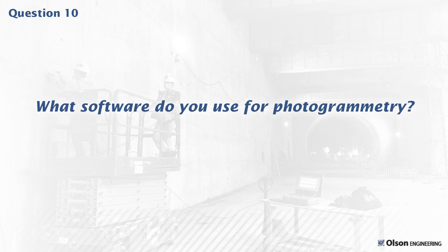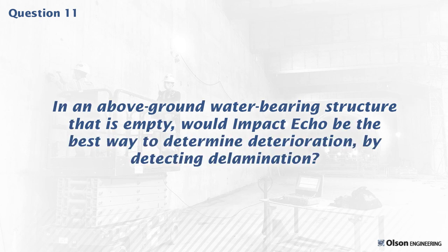Q: In an above-ground water-bearing structure that is empty, would impact echo be the best way to determine deterioration by detecting delamination? Yes, because you'll see both the front and backside steel delaminations — one responds as a flexural response, the other as a thin section echo — and you'll know the depth of the steel. Assuming it's smooth concrete, the impact echo scanner would work well, operating from basically 3 inches and up.